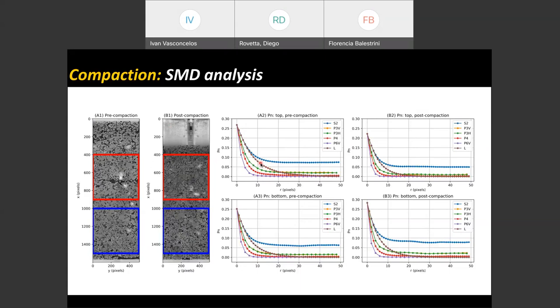But this is another descriptor which we use to decide the size of pores, because where they depart from the two-point correlation functions, we can measure the size of a pore or the average size of a pore. The first thing I want you to notice here is that, remember, I said that at the origin, these values are porosity or volume fraction. At the top, you can see the porosity decreases, and that's very visible in the images. At the bottom, porosity actually increases.